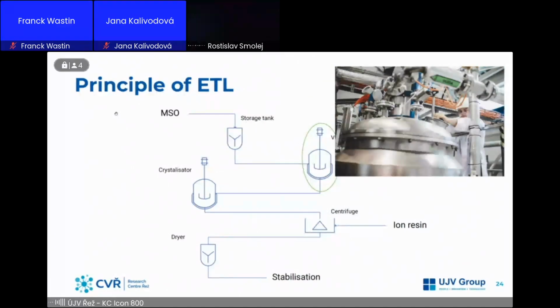Then we have this evaporator. It's a 1.2 cubic meters large tank. It's 2-shelled, so in the outer shell, there's the hot water, which increases the evaporation. And it's also continuously stirred, which is great, and works under vacuum, which further enhances the evaporation process. The tank is a bit smaller, so you can see from the storage tank to the vacuum evaporator, it needs to go into 2 phases.